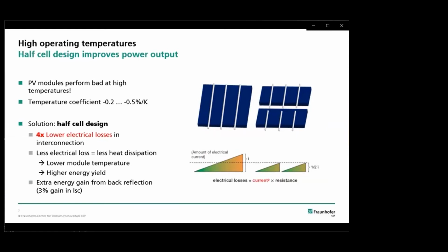Here, starting with the example of high operating temperatures. Generally, PV modules perform badly at high temperatures. So we have a temperature coefficient, which, depending on the PV module technology, is in the range of 0.2 to 0.5% loss per increase in Kelvin. That means that if it's about 20 degrees warmer, you can have at least 10% less output performance for your PV system.